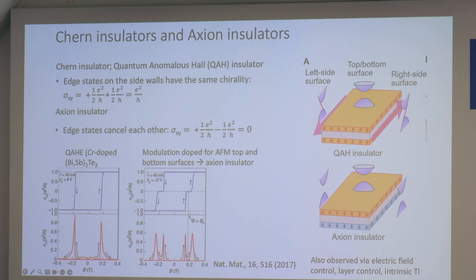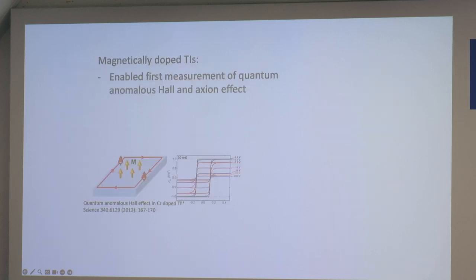Okay, so that's all I'm going to say experimentally about magnetically doped TIs. They really enabled the first measurements of what happens when you couple TIs to a magnetic field. They showed these first measurements of quantum anomalous Hall and axion effects. The problem here is that all of these effects happen at very low temperatures. You have to be below the Curie temperature, which is usually below about 15 Kelvin in the materials of interest.